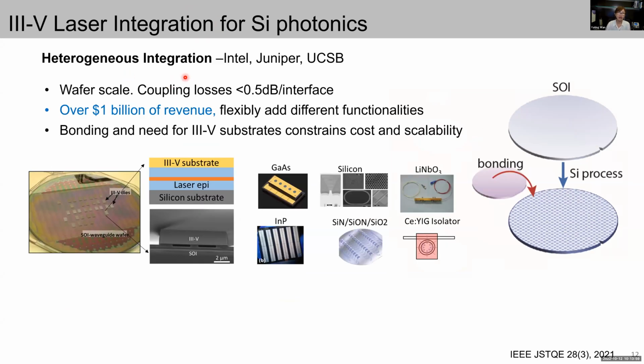So heterogeneous integration, on the other hand, is another technique that bonds the unpatterned III-V thin films to the silicon wafers at the early to middle stage with a coarse alignment, and then we can define the device by lithography on a full wafer scale. So the overall efficiency is very high, reaching coupling loss lower than 0.5 dB per interface. And with the chip maker Intel, this device became the first laser on silicon used in mass-produced products, transceivers, that began shipping by the millions in just the last few years and is generating over 1 billion in revenue nowadays.